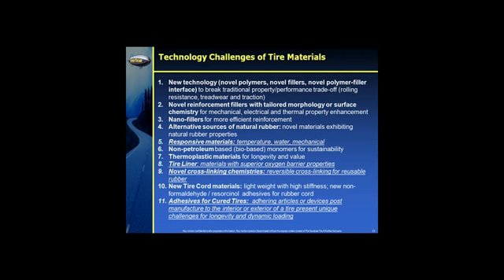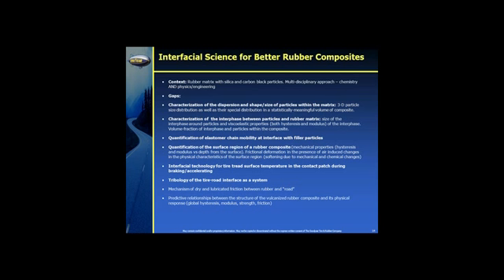Lastly is something that's developing recently, and that's there's an increased number of circumstances where it's beneficial to attach an object to a tire after manufacture. So we need adhesives for cured tires. Circumstances might be to attach something for decorative purposes, or to attach something functional like a sensor. And the challenge in tire polymers is because of the range of polymer substrates in the tire, butyl, natural rubber, or synthetic, as well as the small molecules and fragments in the tire that can migrate to interfaces and possibly degrade adhesion. So how all these work together, I hope you're beginning to see the theme here is that the behavior is at interfaces, and so the interface characterization becomes critical.